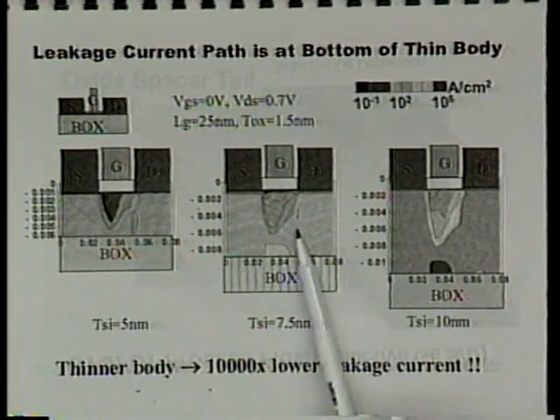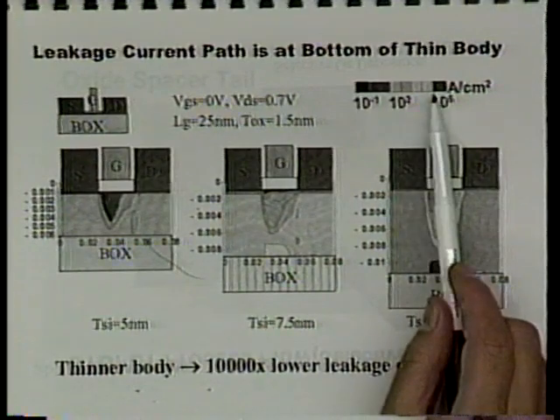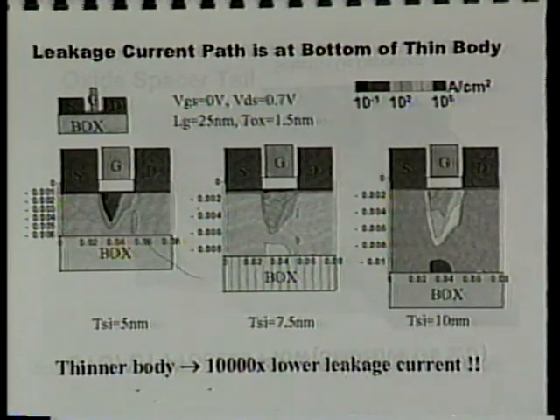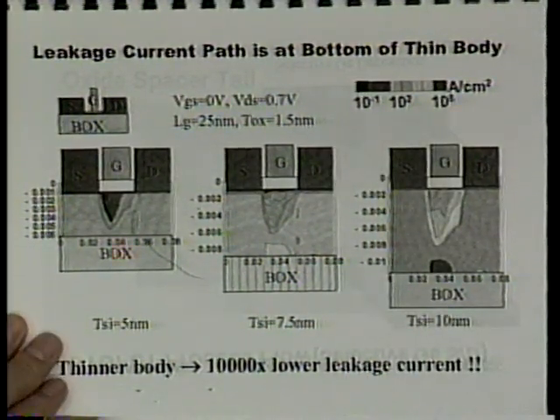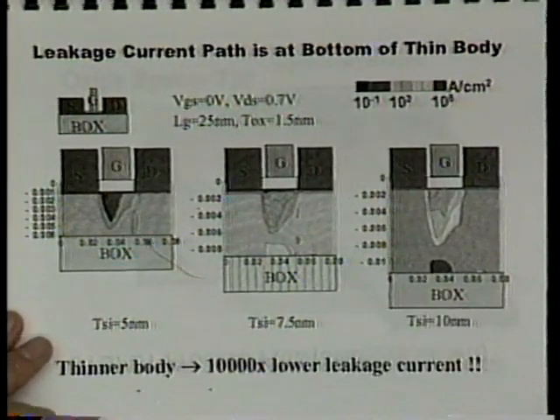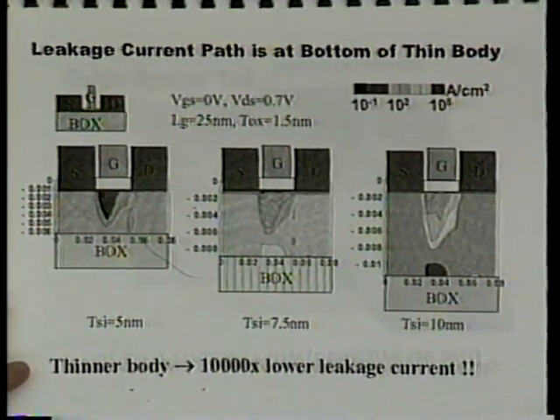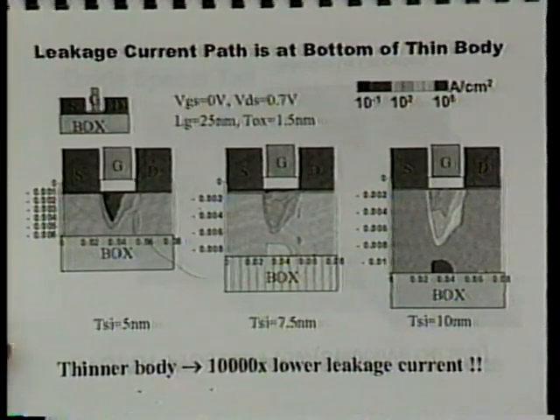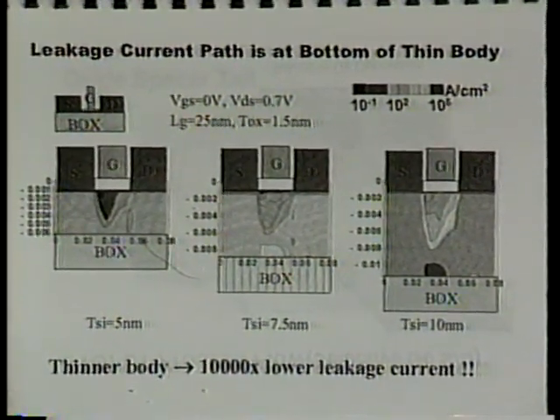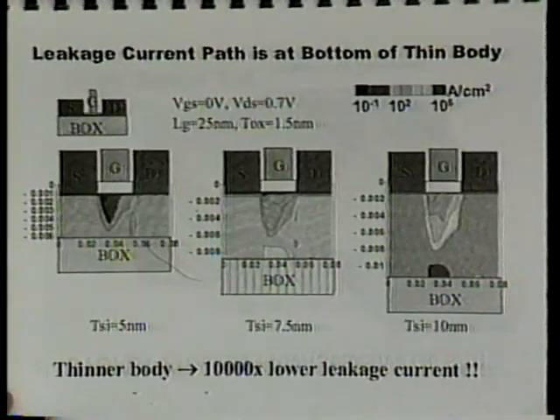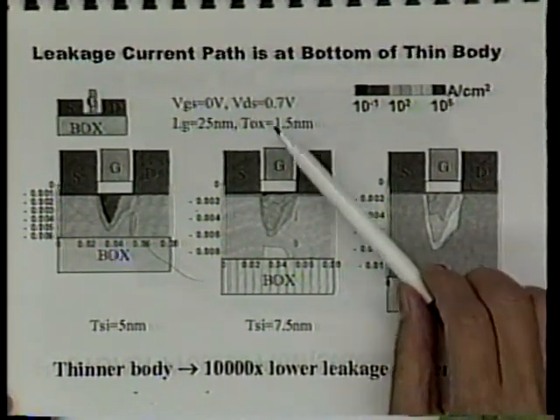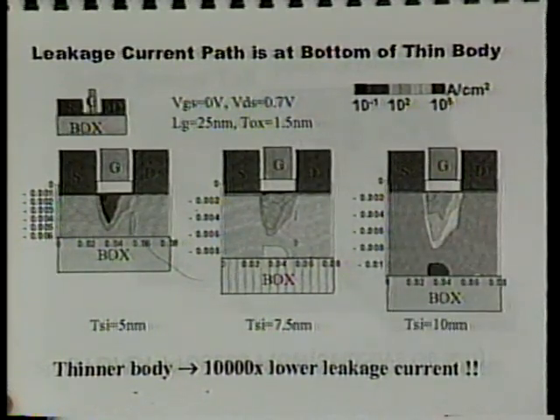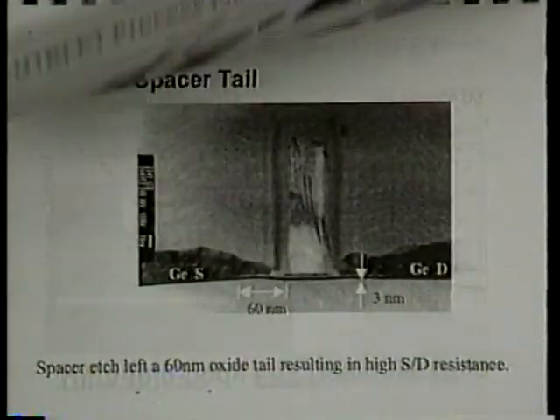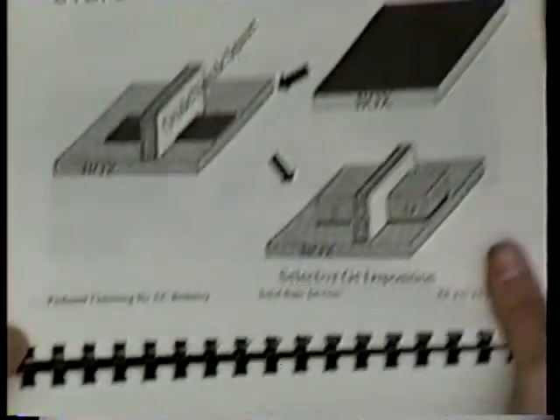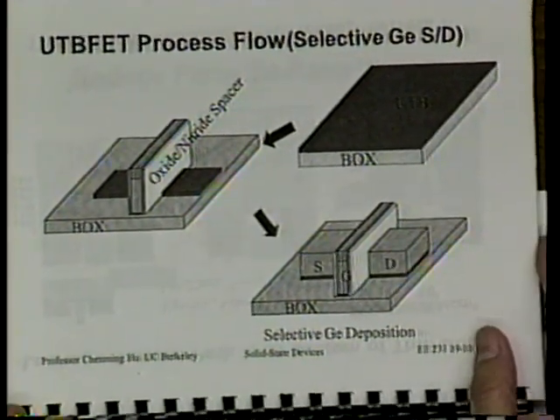So cut out even more. Now this becomes dark because the scheme somehow shows up here. This just shows it dramatically, orders of magnitude, you reduce leakage current. Think about, if you don't do this, how can you reduce leakage current by orders of magnitude? It's very difficult. You're going to raise VT by 0.2 volt, 0.3 volt. Now, what's the impact of that on the performance when the power supply is only 0.7 volt? So that's why the leakage current is something we have to really deal with using clever device structure.